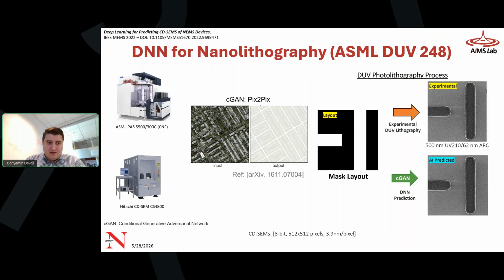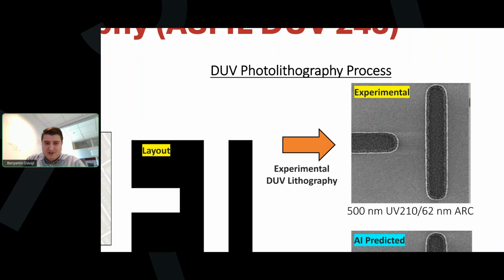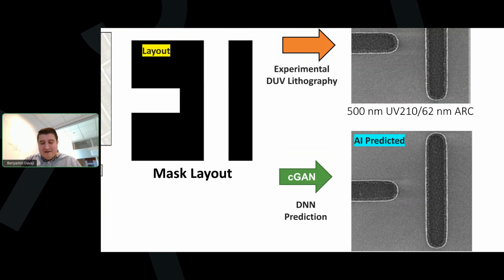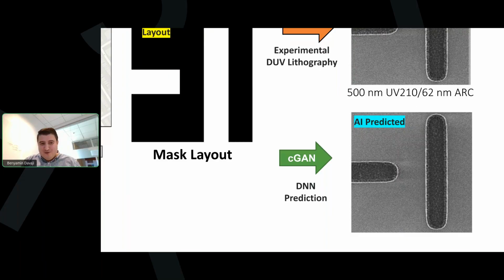At Cornell, we had access to deep UV lithography. We collaborated with Hitachi for automated measurements, and we learned translation between a binary layout and SEM images. The top image is actually the experimental image. You can see that there are some rounding of edges, some roughness of resist, and some imaging artifacts. These are part of the real experimental data, but in the AI predicted world, you don't need to go to the clean room. You can just use a trained model that learns to predict the outcomes.